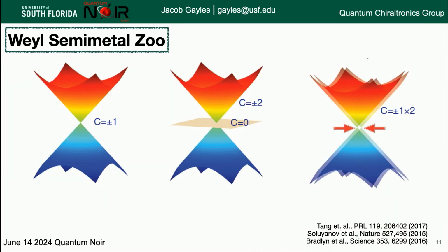Okay, so since that's come, there's been a whole zoo of these Weyl semi-metals. So the first one I showed was this plus or minus 1. You also have some other cases, which is where you have a plane in between, you have plus or minus 2 charge, and you can also have double Weyl fermions. The way you count them is you're looking at the spin, so the spin of the electron in momentum space and how that evolves, and you have to always do this contour integral in the imaginary plane, of course, to get counted, and you always have to go in the same direction.